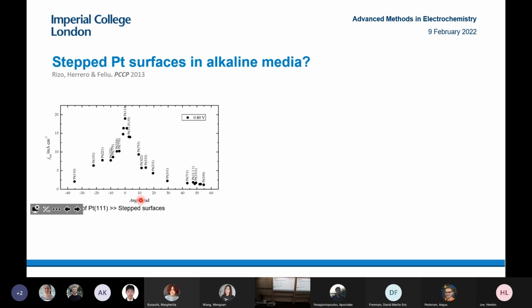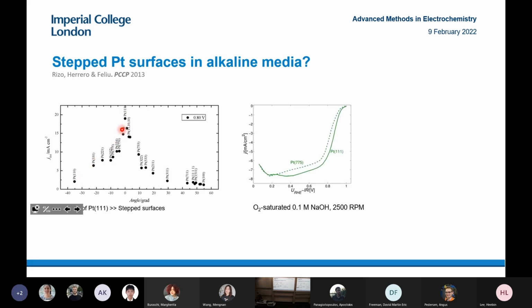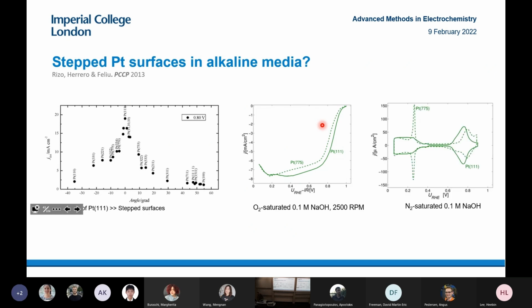So anyway, when we look at stepped surfaces in alkaline media, this is showing the oxygen reduction activity on platinum 111. As you introduce steps, as you go away from platinum 111, you actually see a lower activity. So this is the opposite of what happens in acid. This is an example here on platinum 775, you see lower activity. So introducing undercoordinated sites, it's less active.